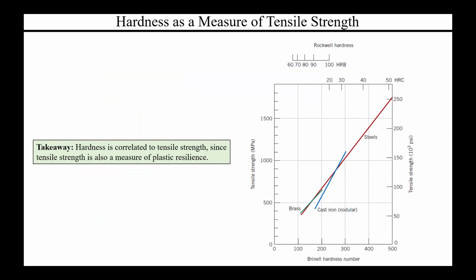And as you can imagine, hardness and something like tensile strength are absolutely correlated. So in this case, the x-axis is a hardness number for a particular type of test, a Brinell hardness test, and the y-axis is tensile strength. If you have multiple materials, say you take cast iron and make many different samples of cast iron, or you test it in various spots within your cast iron sample, what you'll find is that as the hardness goes up, and again, the hardness is that test of localized plastic deformation, you'll notice that a sample that has an overall larger hardness is going to have a larger tensile strength. And this makes sense, right? If the plastic deformation is occurring at a smaller hardness, meaning less energy was required to plastically deform it, then that would ultimately mean that the material is likely going to have a smaller tensile strength because it's just an overall weaker material.